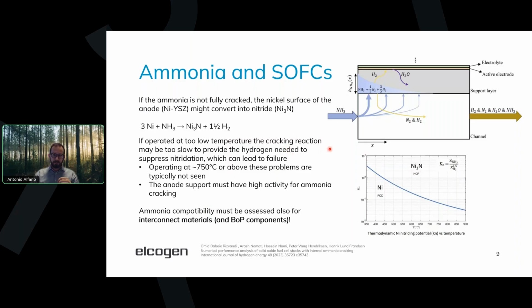In the case of solid oxide fuel cells, the cracking of the ammonia can happen in the support layer of the unit cell, and the rate at which this reaction happens is again dependent on temperature. So the balance between the cracking of the ammonia in the support layer and the reactivity of the unit cell, but also of the other components, to nitridation eventually determines the operation window of a given stack or a given cell for a given temperature to ammonia. Generally speaking, at around 750 degrees C, the cracking process of ammonia is sufficiently fast to provide sufficient hydrogen to prevent the nitridation process.